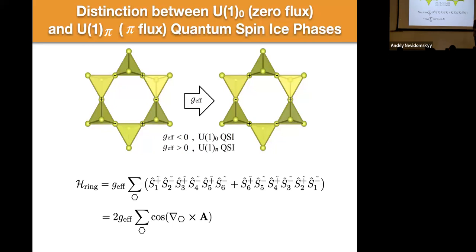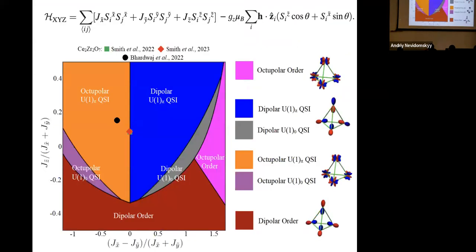I'm actually curious, can you show the phase diagram where you put the parameters of cerium 227? So you believe that the parameters are right in between? How do you experimentally really separate whether it's octopolar or dipolar quantum spin liquid? Yeah. So at some level, I would say it doesn't matter. There are interesting things associated with being close to this boundary, but anywhere in the neighborhood of here, you have very significant dipolar and octopolar correlations, right?